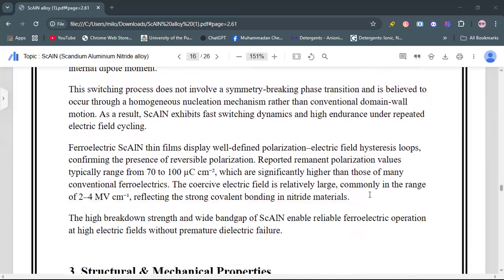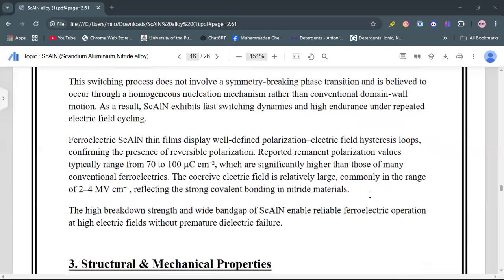Ferroelectric scandium aluminum nitride thin films display well-defined polarization-electric field hysteresis loops, confirming the presence of reversible polarization. Reported remnant polarization values typically range from 70 to 100 microcoulomb per centimeter squared, which are significantly higher than those of many conventional ferroelectrics. The high breakdown strength and wide band gap of scandium aluminum nitride enable reliable ferroelectric operation at high electric field without premature dielectric failure.